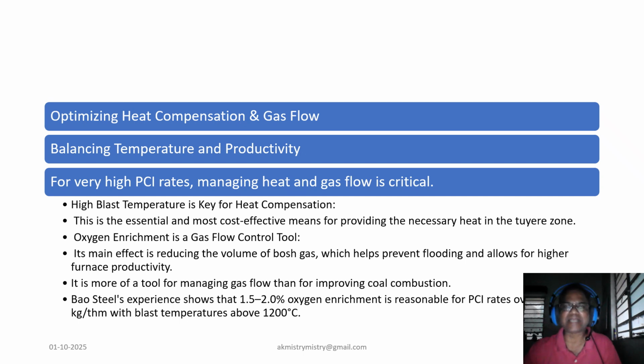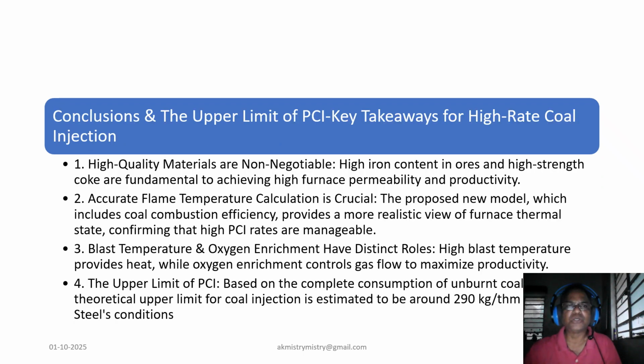With this understanding, we can see that blast temperature and oxygen enrichment play two very distinct and important roles in high rate PCI operation. The primary and most cost effective method for heat compensation is a high blast temperature. It provides the necessary thermal energy to balance the cooling effect of injected coal. Oxygen enrichment, on the other hand, should be viewed mainly as a gas flow control tool. Its main benefit is not raising the temperature but reducing the volume of gas in the furnace. This helps prevent flooding, which in turn allows for higher furnace productivity. In China, the cost for a 100-degree blast temperature increase is only about half that of a 1% increase in oxygen enrichment, making it the preferred method for heat.